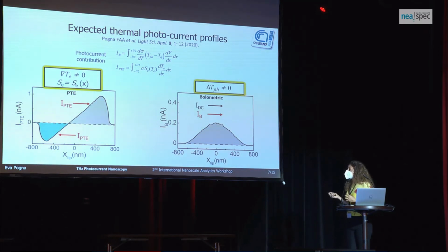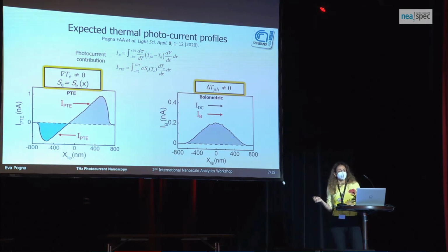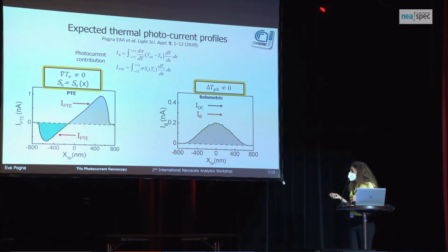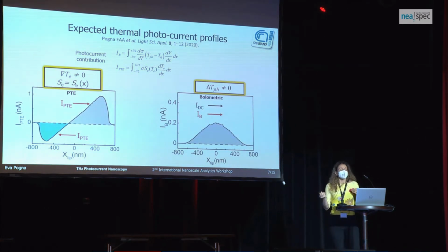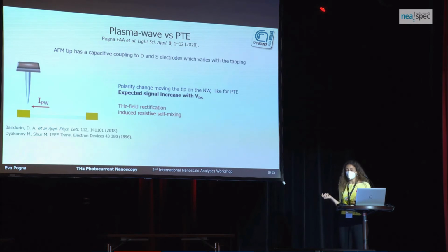And interestingly, the two effects would give rise to very distinct line profiles. In the case of the photothermoelectric effect, we would expect to see a change in the polarity, because the electron will go towards the cooler part of the material. So, as the tip moves across the nanowire, we will see a change in the direction of the electron flow. Instead, in the case of bolometric effects, we will see the highest current where we have the highest lattice temperature, and a constant polarity across the nanowire.